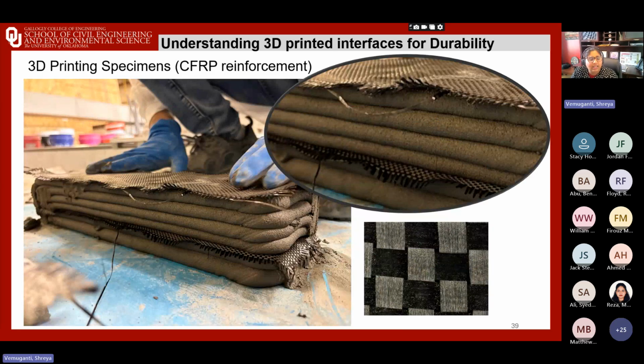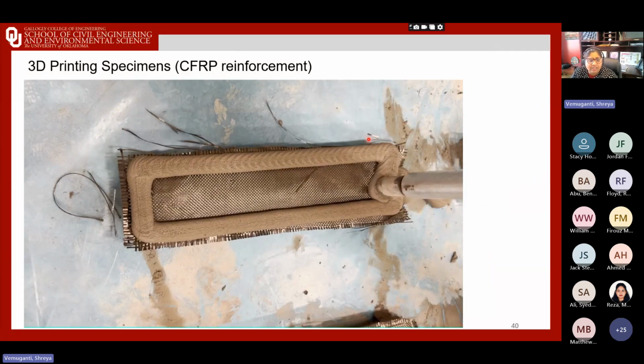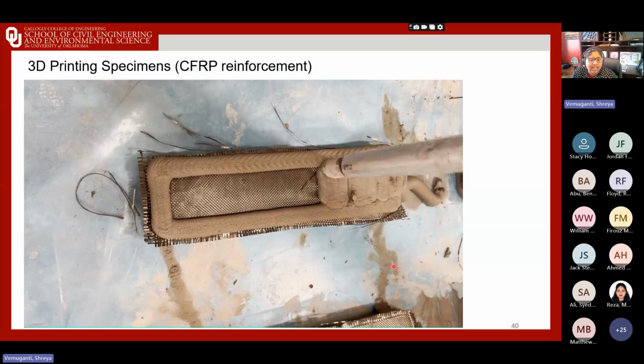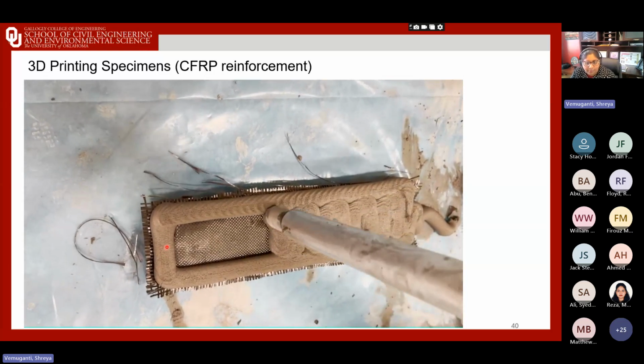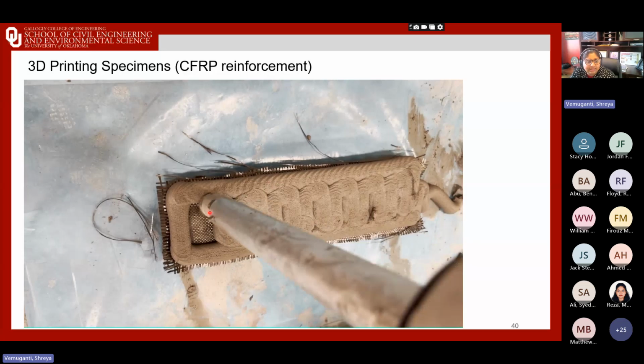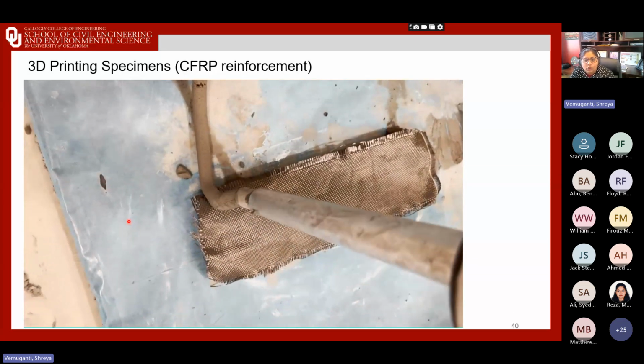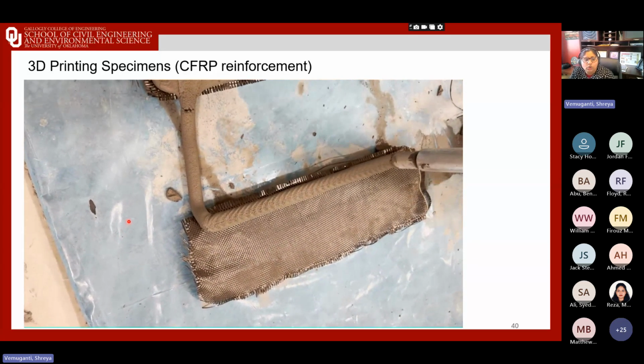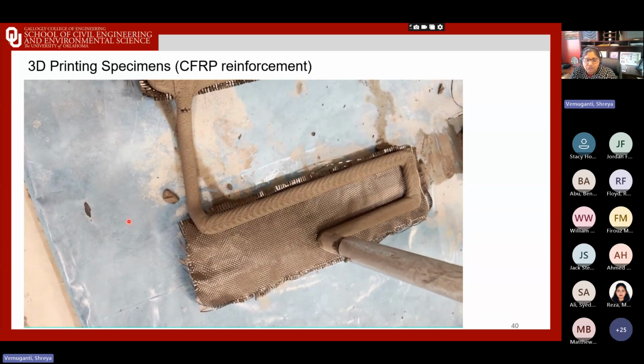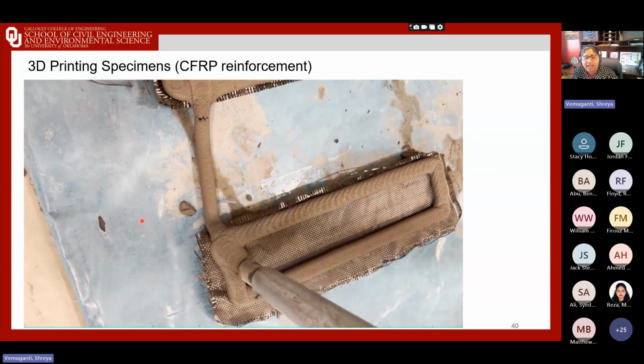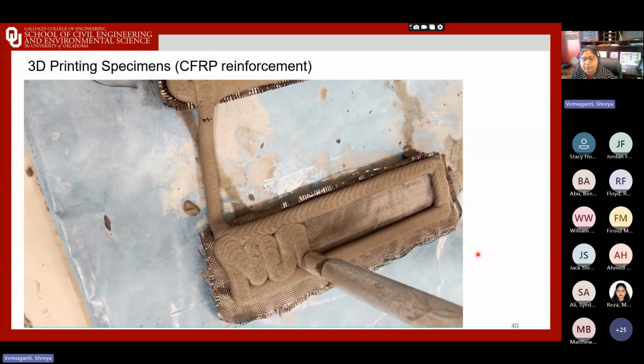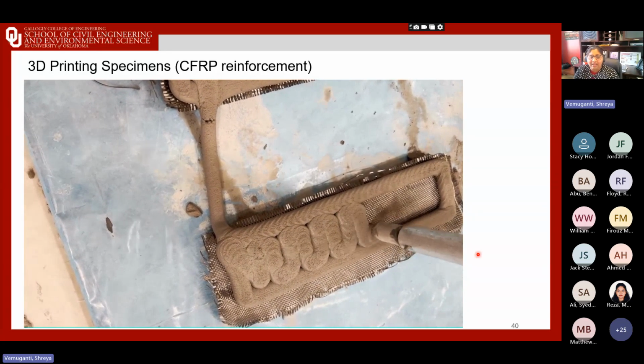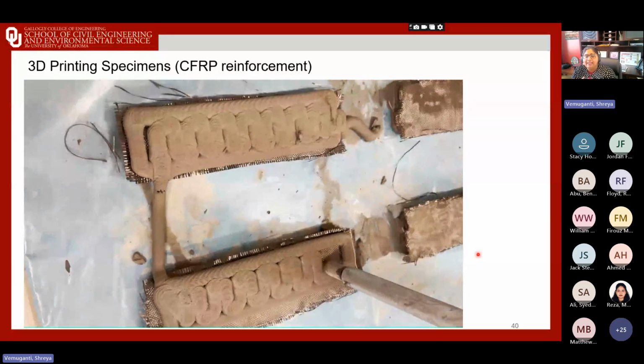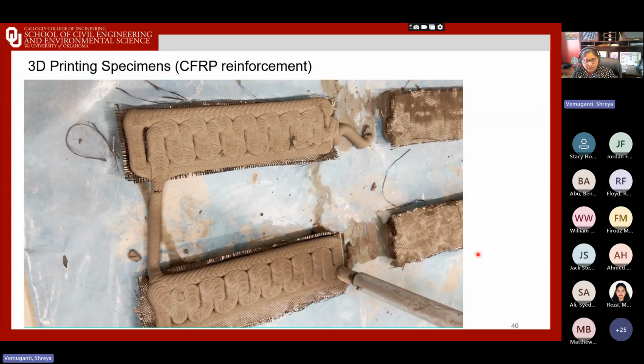Here you see the carbon fiber placement itself, again, bottom second layer and top second layer. A very interesting parameter to this printing is notice that there is no external compaction applied to the layers, right? The nozzle itself, when it's printing, provides that inherent compaction as it deposits the material. So this creates that pressure that actually stretches this embedded fabric during printing. And the stretching is important because how the reinforcement is anchored at the interface gets affected, right? And that will influence the bond quality and also the long-term effects that we are trying to look into